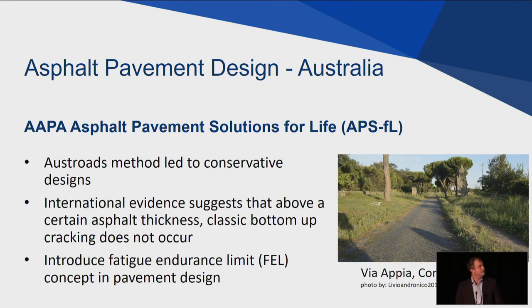So against that background, the Australian Asphalt Pavement Association started the Asphalt Pavement Solutions for Life project, recognizing that the Austroads method led to various conservative designs, again, especially in the warmer parts of the country, and also looking at the international evidence that was suggesting that above a certain pavement thickness, classic bottom-up fatigue cracking that we're designing for does not occur. So they were looking to introduce the fatigue endurance limit concept in the Austroads pavement design method.